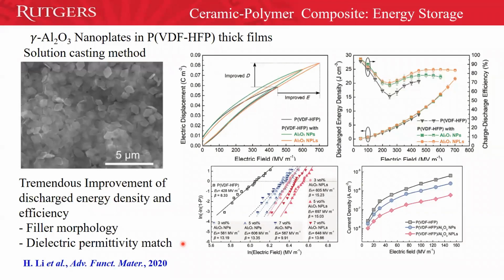Again, this is another outstanding paper from Penn State MSc department, and this is on gamma alumina composites. They look at not only alumina, they look at titanium, they look at silicon. And here the gamma alumina is kind of an anisotropic particle. It's like platelet or flake geometry, highly loaded.